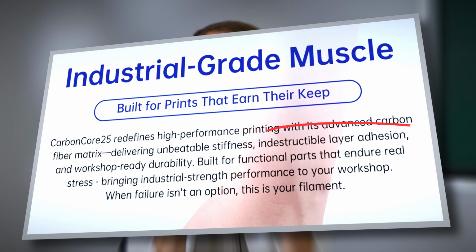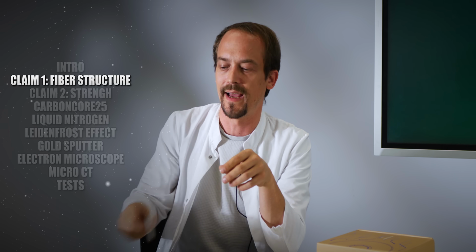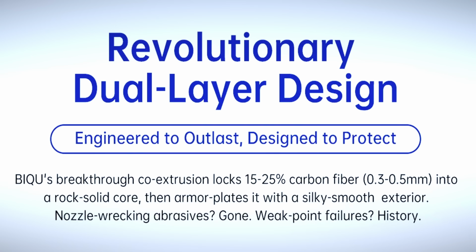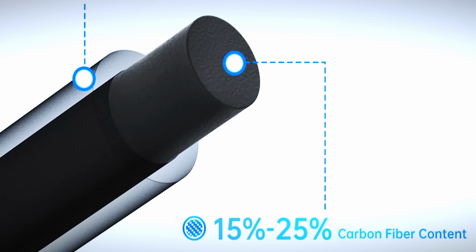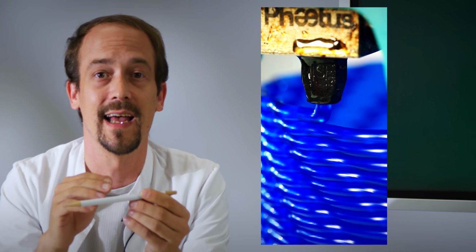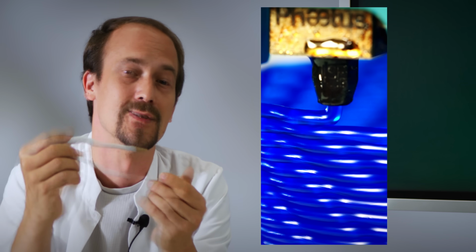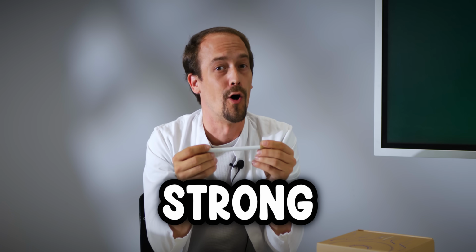Their magic trick is something called coextrusion, where they take a piece of carbon fiber filament and wrap it in pure PLA. Just think of the toothpaste you had as a child with the colorful lines in it. The idea is that pure PLA loves to stick to pure PLA, so layer bonding will be very strong. Also, because of the PLA sleeve, your printer will be protected from wear and tear because the fibers never touch your gears or nozzle.